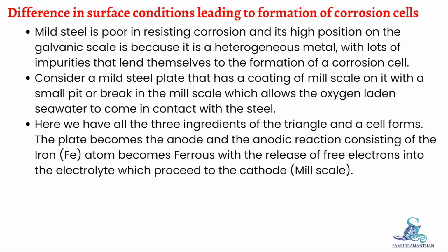Mild steel is poor in resisting corrosion and occupies a high position on the galvanic scale. This is because it is a heterogeneous metal, containing impurities that readily lead to the formation of corrosion cells. Consider a mild steel plate coated with mill scale, but with a small pit or break in the mill scale. Through this break, oxygen-laden seawater comes into contact with the steel. At this point, all three ingredients of the corrosion triangle are present, and a corrosion cell is formed.